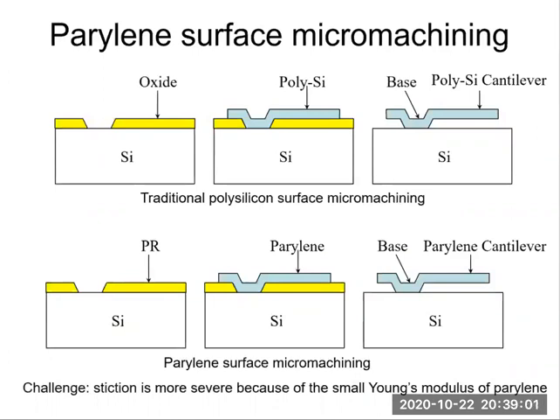Let's compare parylene surface micromachining with polysilicon surface micromachining. In traditional polysilicon surface micromachining, which is shown in the above figures, oxide or PSG is a sacrificial layer. Polysilicon is a structural layer. In parylene surface micromachining, photoresist is typically used as the sacrificial layer, PR, photoresist. And the parylene is a structural layer. So we can clearly see the differences and similarities between polysilicon surface micromachining and parylene surface